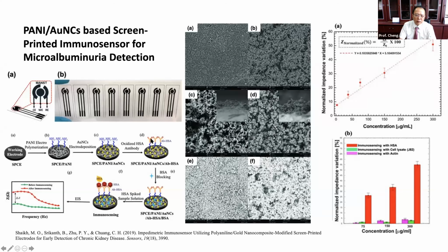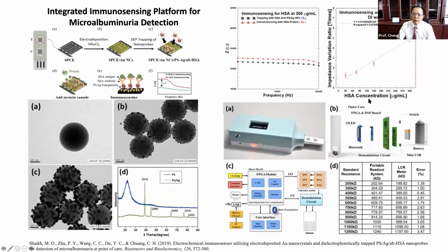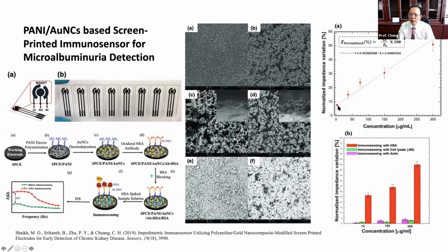Then we directly bond the antibody onto the polyaniline surface. Then we can test the urine, protein urine. We still measure the impedance difference. As you can see, the sensor is very sensitive. Last time we could only achieve this part, but for this nanocrystal nanostructure sensor, we can achieve 3 microgram. That means we can already detect the stage 1 CKD, or even lower,